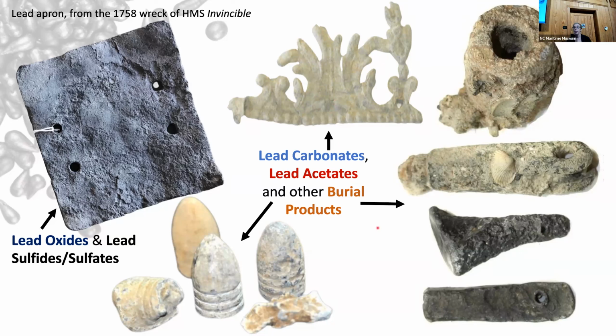So generally with lead, as long as it is not actively corroding, we tend to leave it alone. The one instance where we might not leave it alone, even if it is not actively deteriorating and falling apart, is when we want to see if there's anything on that surface that might be hidden underneath these more voluminous corrosion products, these carbonates and acetates and other types of burial material. So we will at those times make the decision to try to remove this material.